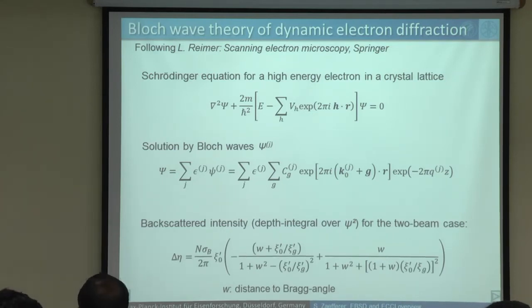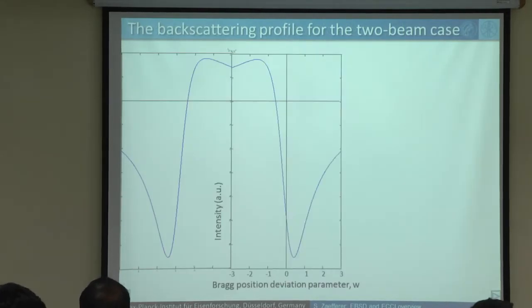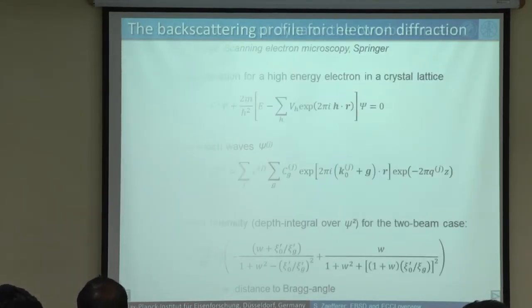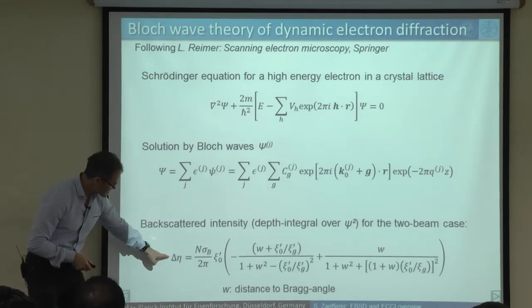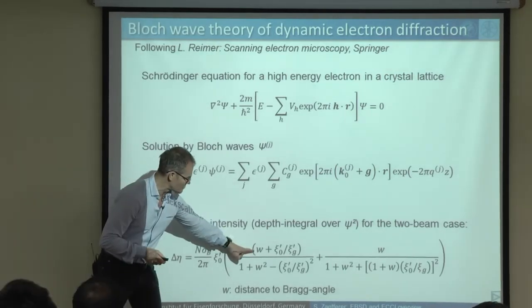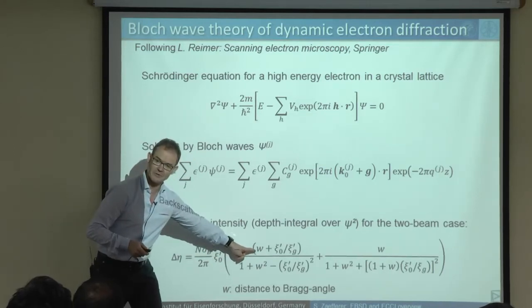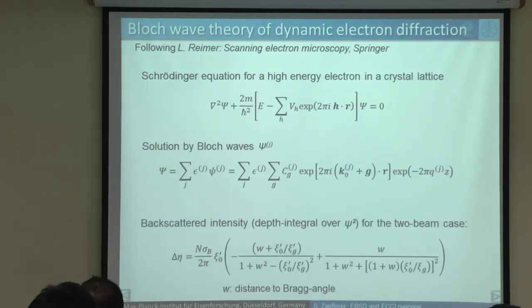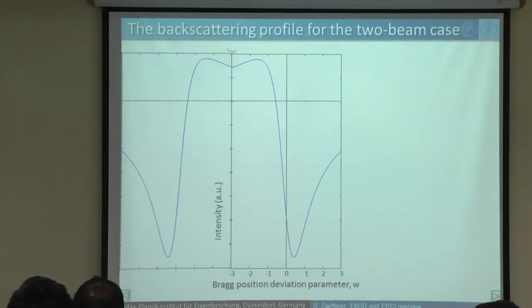If you are able to solve partial differential equations, you can follow this line here. That's a bit too short for following it, but you can in principle find it in textbooks. And what you then do is you get an explanation of the electron intensity in dependence of a variable W. And this W is called, let me think, yes, exactly. We call it the deviation parameter, W, Bragg deviation parameter.